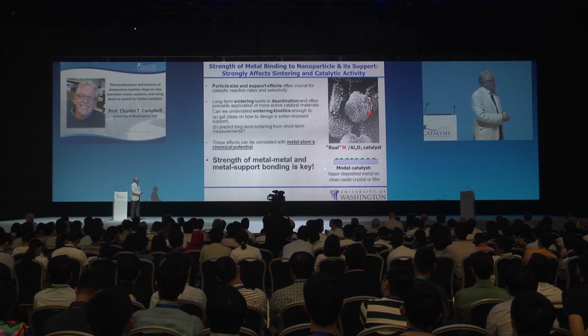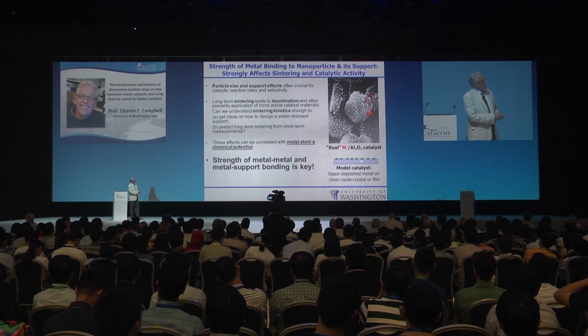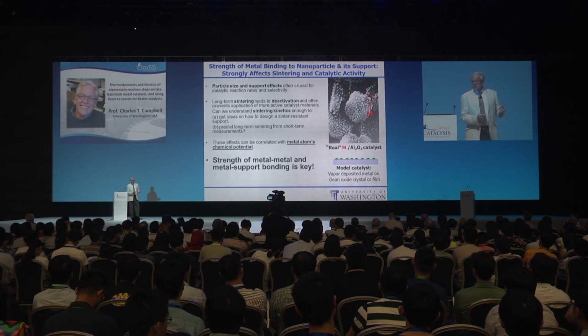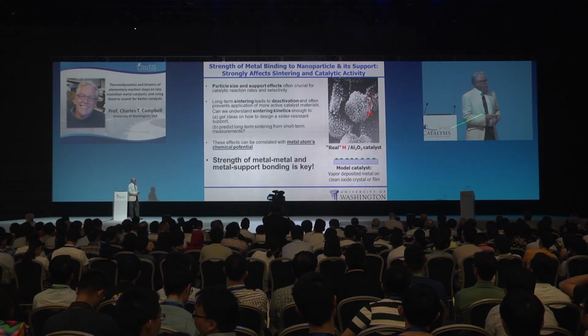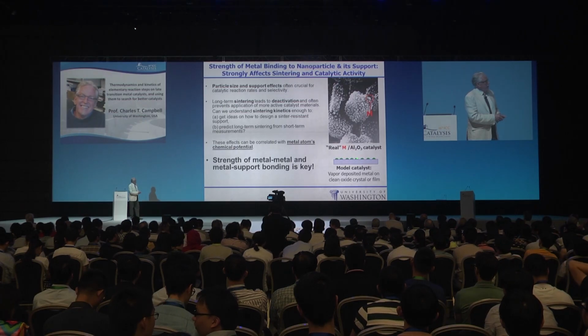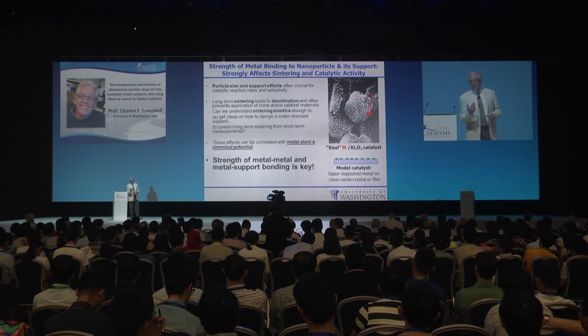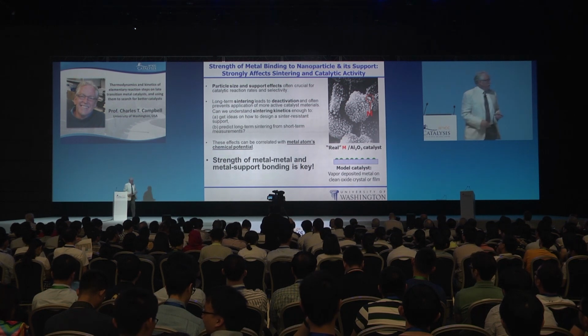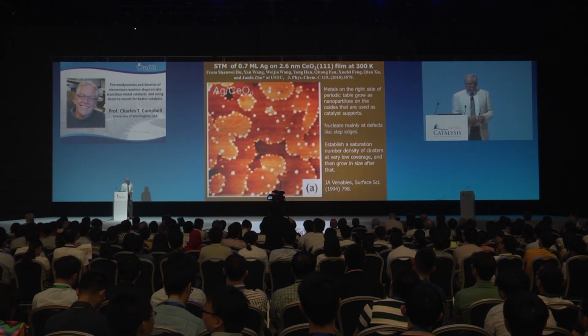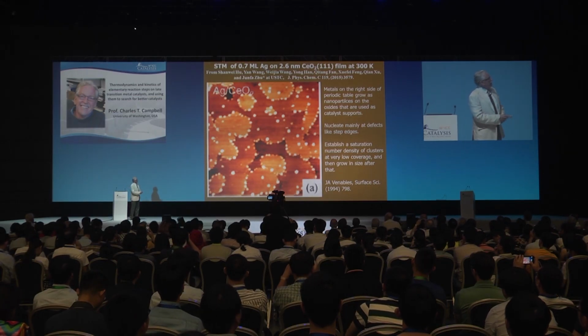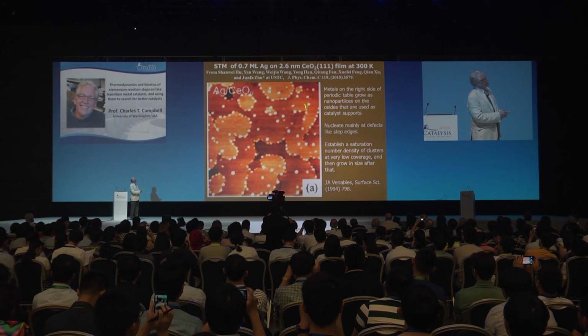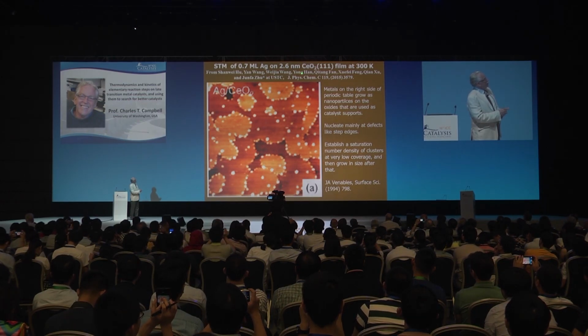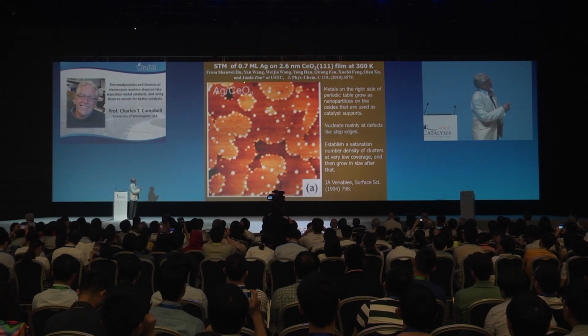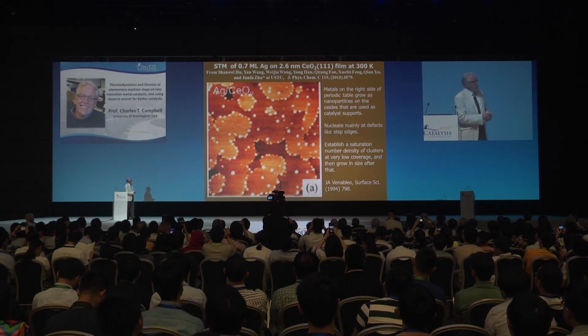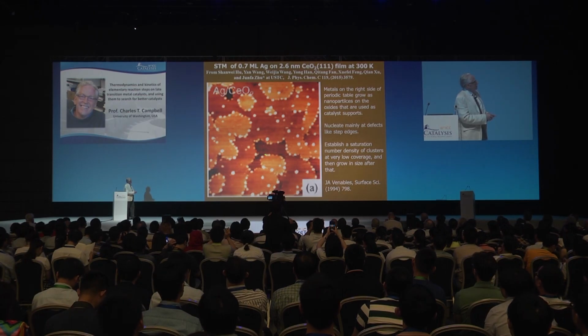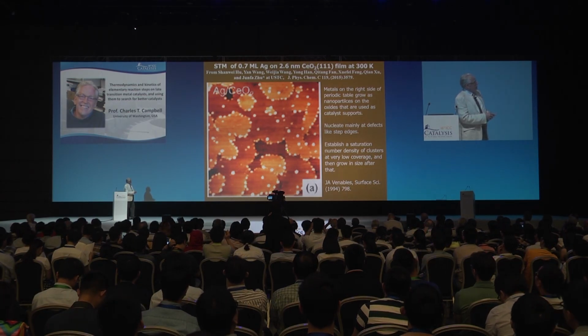And to show that, we resorted to model catalyst again based on single crystal surfaces, in this case single crystal oxides, as models of the support material, and metal nanoparticles that are grown on those by vapor deposition of gas phase metal atoms. And so here's an example of the type of model catalyst that I'm going to be talking about that has silver nanoparticles on cerium oxide. And this is from nice, beautiful STM images from USTC and Junfa Zhu's group. And you can see that the particles decorate the step edges on the ceria.